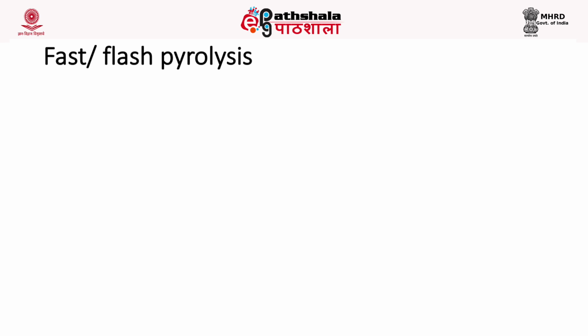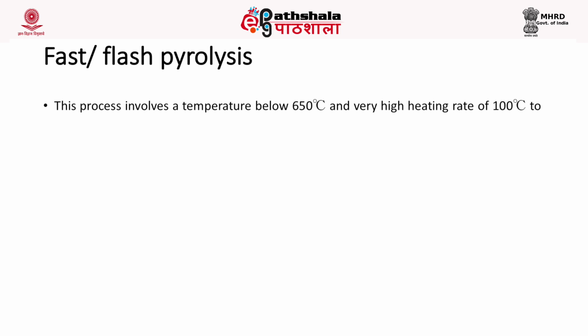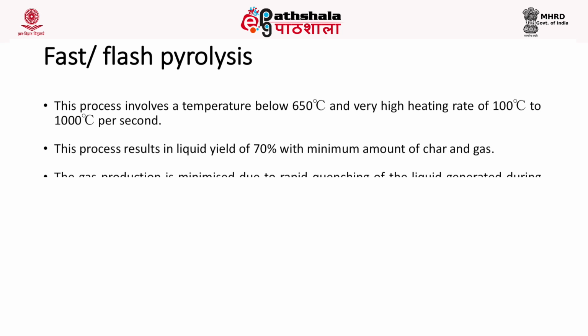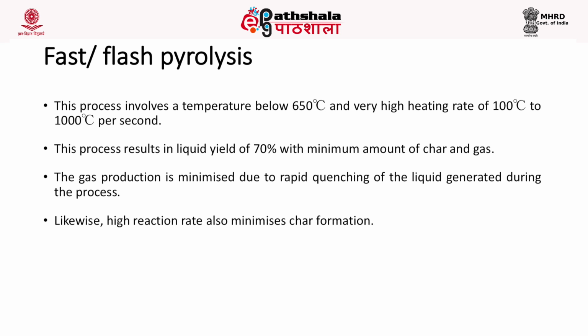Since the process involves slow heating rate and slow removal of products from the pyrolysis unit, the formation of secondary reactions is very frequent. Now, the fast or flash pyrolysis involves a temperature below 650 degrees Celsius and a very high heating rate of 100 degrees Celsius to 1000 degrees Celsius per second. This process will result in a liquid of 70% with a minimum amount of char and gas. The gas production is minimized due to rapid quenching of the liquid generated during the process. Likewise, high reaction rate also minimizes the char formation. Generally, wood and tire are pyrolyzed using the flash pyrolysis process.